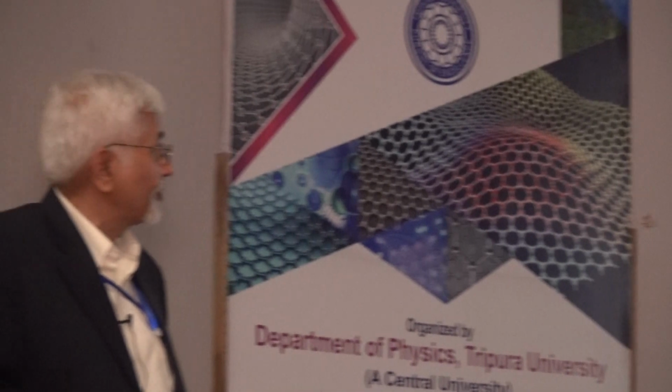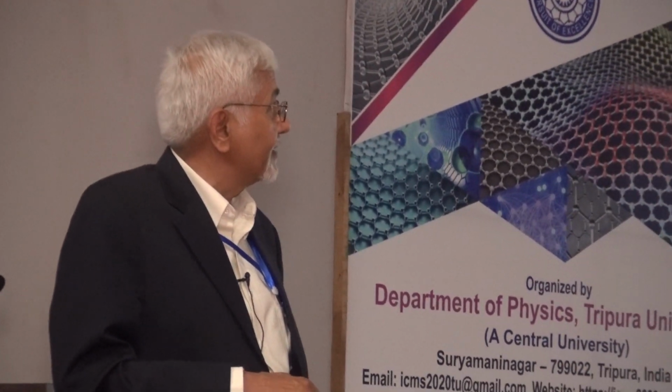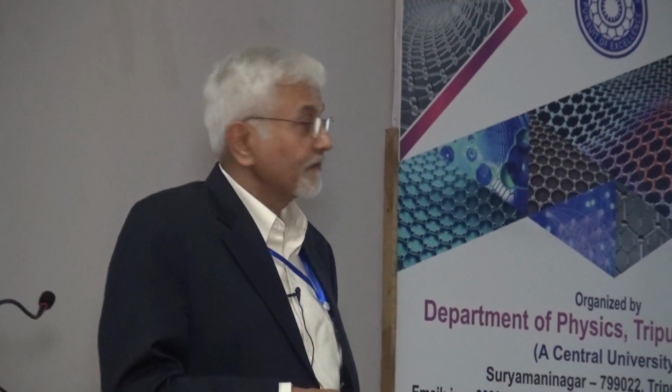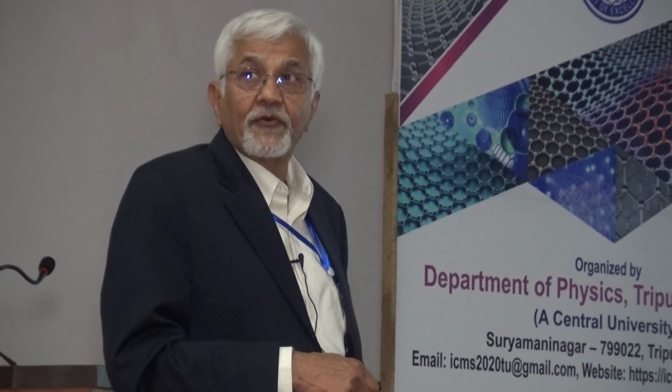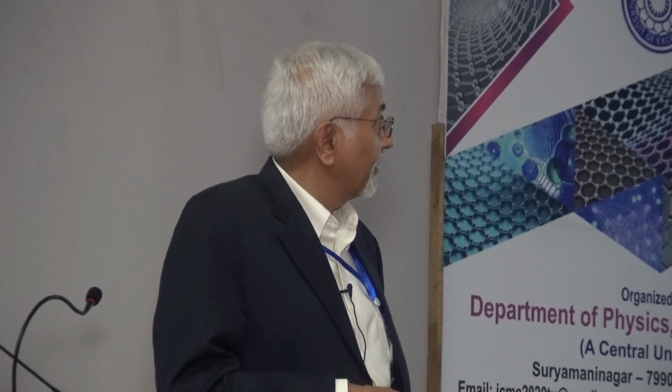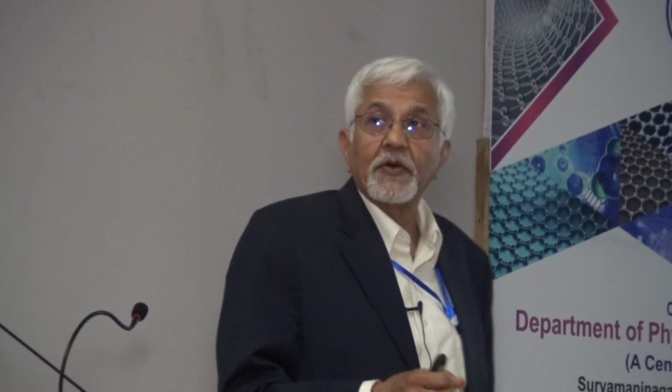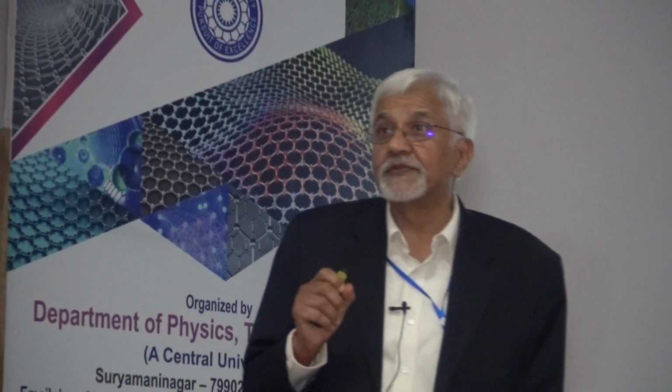And interestingly, if you look at the calculated band structure, if you go from number of layers 1 to bulk, it's sort of like convergence. So monolayer has about 1.4, 1.5 electron volts. For the bulk, if you come down, it's about 0.3, 0.48. So the tunability comes in, depends on the layer thickness of the material.